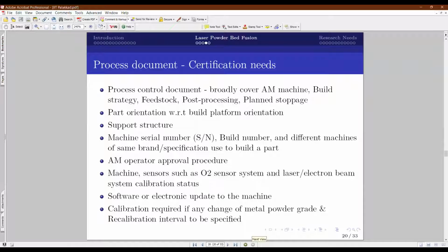Then the process document. We look at the process parameter freezing, and there are other aspects you have to look at, like the process control document, which broadly covers what the AM machine and its make are. For example, if you build a component with an EOS machine, and tomorrow you go with an SLM machine, then the entire thing will change. Or different other processes like direct energy deposition. Similarly, the build strategy, like the build orientation, and the raw material source, where you buy the powder from, post processing, and during the build, did you intentionally stop, or was there any unintentional stop? All these things should be captured. Then the way in which the build support structure or the part is oriented with respect to the platform should be captured, along with the machine serial number and build number, if different machines of the same brand or specification are used to print a part.